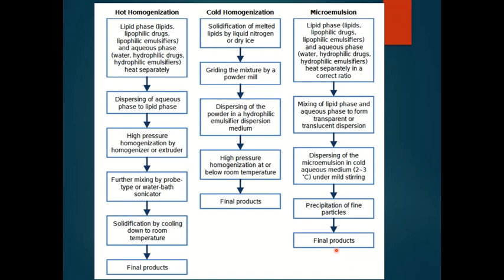But the only thing is you need a little higher concentration of surfactants to get the microemulsion, and you need to produce the microemulsion by a hit and trial method and then dilute that. The disadvantage of this system is you will get a very dilute dispersion of particles. Approximately, if you dilute it to 1 liter, you will have hardly 1 gram of particles. So 1 gram in 1000 ml, you think of that. It is very dilute, so during the evaporation stage you may have problems.